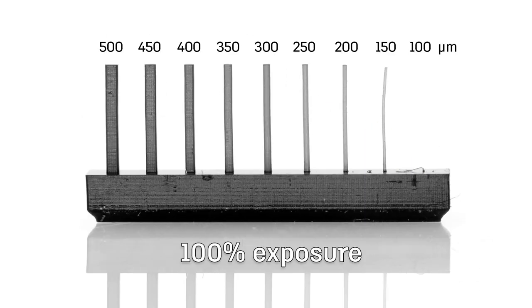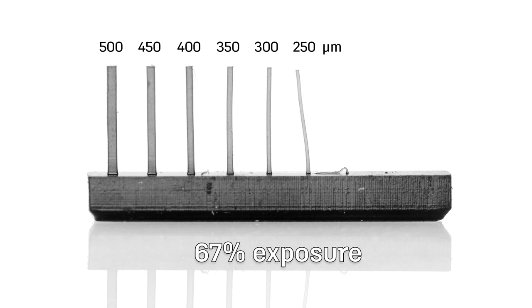It started to print, but collapsed because it was too thin. When we print this model with only 2 thirds of the energy, neither the 150 or 100 micron posts are formed.